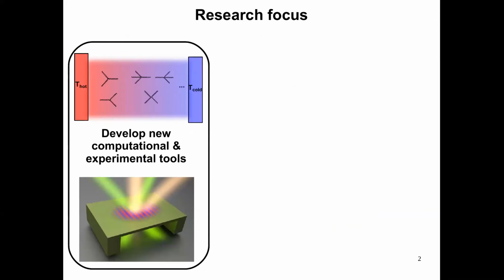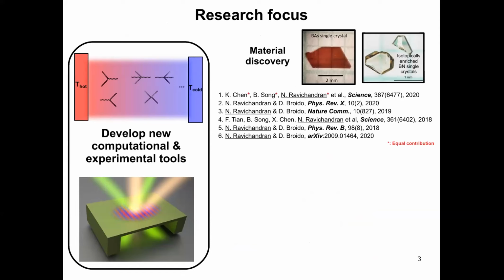So my research focus, just to give you a broad overview, is to develop new computational and experimental tools to probe the microscopic interactions among energy carriers in electrically insulating and semiconducting materials. Using these tools, I have worked on problems such as discovering new material candidates with extreme thermal properties. For example, here I'm showing a couple of pictures of new materials that we discovered using this framework. One of them is this boron arsenide single crystal. Another one is an isotopically engineered enriched form of boron nitride crystals, both of which have a thermal conductivity exceeding 1000 watt per meter Kelvin at room temperature.